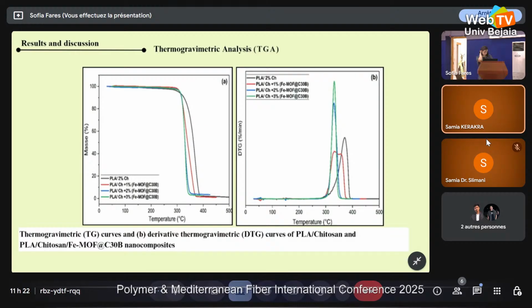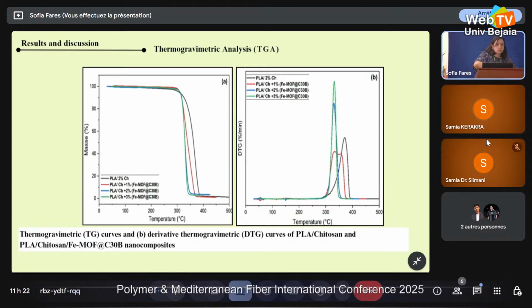TGA analysis. Here, as we can see, the DTG curves show wider degradation peaks, suggesting altered degradation behavior. After the incorporation of the MOF into the PLA, the degradation accelerates. We can say that this incorporation accelerates the depolymerization of PLA, but still no significant structural impacts, making the composite suitable for food packaging.